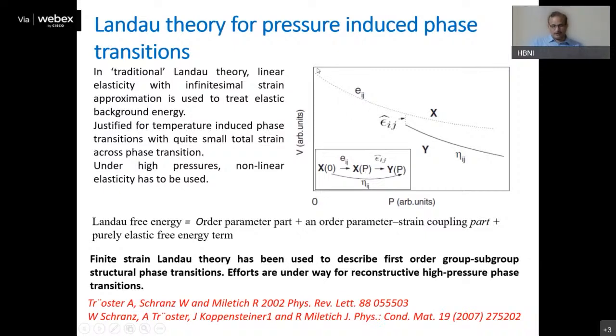Because our first phase itself is not transforming to another phase, but it is evolving, and there is some elastic strain continuously building up. So this actually acts as a background for this phase transition. So this part also has to be included in the Landau free energy. And this way, the high pressure phase transitions can be described with the Landau theory.